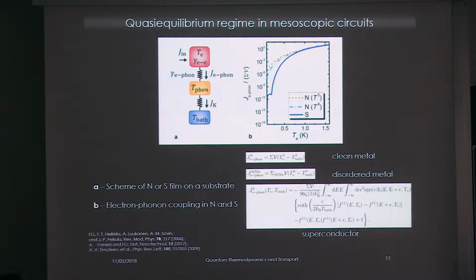And then the metal film is deposited on top of a substrate, so there is an additional interaction due to the interface resistance, the well-known Kapitsa resistance. Depending on how large the Kapitsa resistance is, the temperature of the substrate can be different from that of the phonons in the system. But typically, on very small structures, these are almost equivalent. So we make the assumption that typically the phonon temperature coincides with the bath temperature, and the electronic temperature can be completely different from this one.